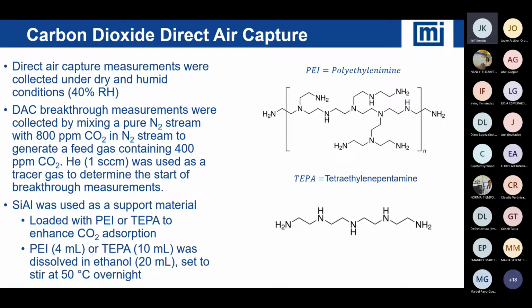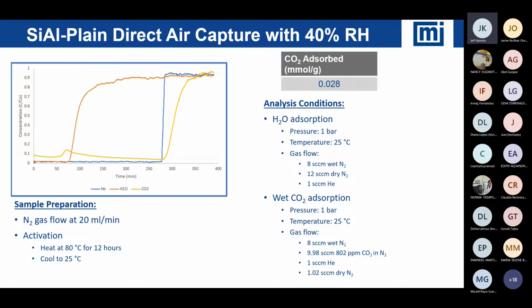With CO2 capture, one area that people have been quite interested in is, if I have a solid, can I enhance the performance? And one way is to take an amine and support that amine on the solid. Amines are quite effective for CO2 capture. They've been used in the liquid phase for many decades industrially for CO2 scrubbing. So amine technology is quite well developed, but now if we combine it and put it on a porous material, how can we use it? Right. So here's the nice benefit of now looking at breakthrough. We can use water in the mix, right? So using breakthrough type of analysis in these dynamic experiments, we've got to be more careful.